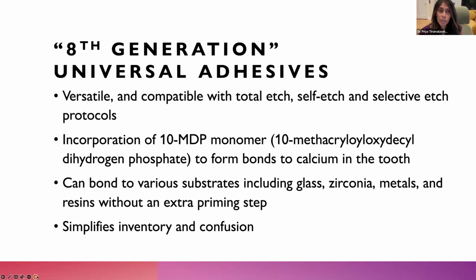So the latest addition to our armamentarium of adhesives are the 8th generation or universal adhesives. And the benefit of these adhesives is that they're very versatile. They're compatible with whichever protocol you want to use, whether you use total etch, self-etch, or selective etch. And the key piece is that there's incorporation of 10-MDP monomer that helps to form bonds to calcium. And amazingly, one bottle can bond to various substrates, including glass, zirconia, metals, and resins without using that extra priming step or a separate bottle.